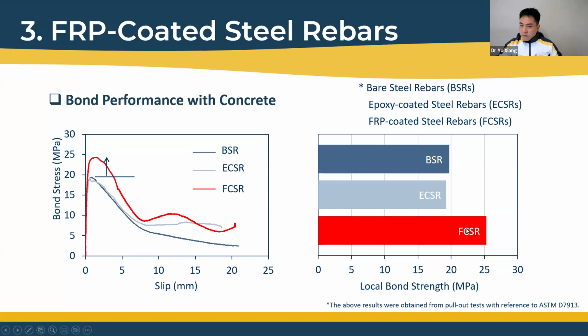But the FRP coated steel rebar had a bond strength much higher, even higher than that of bare steel rebar. From the bond stress and slip curves, these two lines are for bare steel rebar and epoxy coated steel rebar, and the red line is for FRP coated steel rebar. For each line, it is an average of 3 samples.